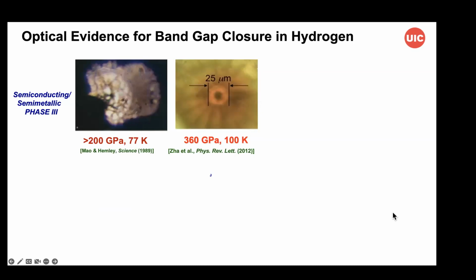Just very briefly, we focused on optical studies over the years, and the very first observations of so-called black hydrogen go back to 1989, when we found it in heterogeneous samples at pressures above 200 GPa. At that time, we couldn't measure pressure above 200 GPa, but we estimated it was some pressure above 2 megabars. That one has this band gap closure. We could not determine whether it was a metal or not, but there was evidence for band gap closure.